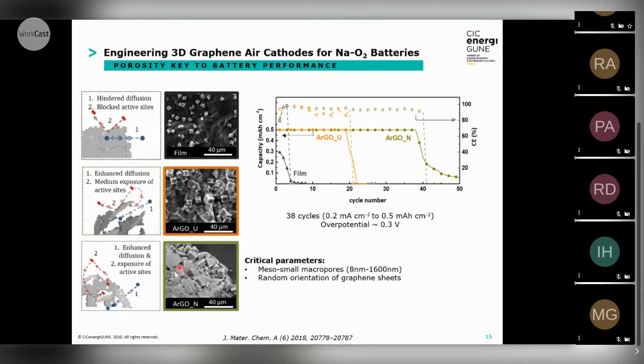In the case of the best performing samples, we have seen that this is really a 3D structure where all the graphene sheets are randomly oriented, and then the oxygen diffusion is easy. We can reduce it, and then we can form all this discharge product on the surface. So the critical parameters in terms of the cathode porosity are to have meso, small and macropores, and the random orientation of graphene sheets is really important. But there is a problem: this method is very tedious, it's a very aggressive process, and we need to do a post-synthesis method.